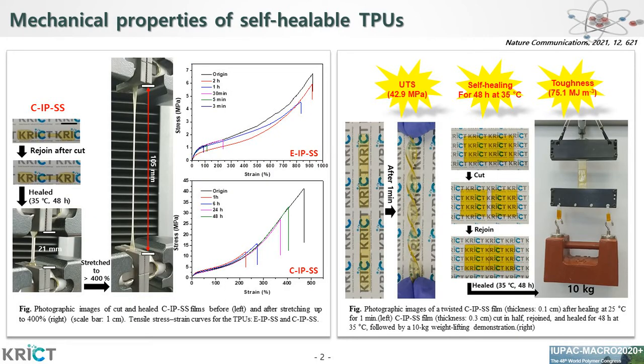Interestingly, CIPSS exhibited significantly superior mechanical properties compared to other self-healing materials. The outstanding tensile property of CIPSS has little penalty on its self-healing efficiency. CIPSS films were cut in half, reattached, and then allowed to recover at 35 degrees Celsius for varying amounts of time. After 48 hours, the recovered CIPSS is as strong as commercial urethane. And another cut and rejoined film with a contact cut area was able to readily lift 10 kilograms of weight.